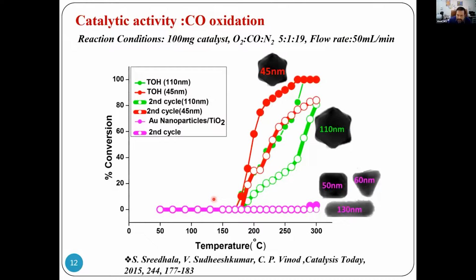Now we do see oxidation activity from these nanoparticles. This trisoctahedral nanoparticle, which is around 45 nanometers and 110 nanometers, shows catalytic activity above 150 degrees Celsius. Whereas if you make a cube-shaped particle, a triangular-shaped particle or a rod-shaped particle, which are basically low-index faceted nanoparticles, they really don't show any catalytic activity under the temperature regime through which we run this particular reaction. So even though the size of these nanoparticles is very, very high, they can still show catalytic activity, which shows that it is the undercoordinated sites present on the gold nanoparticle that are the active sites for